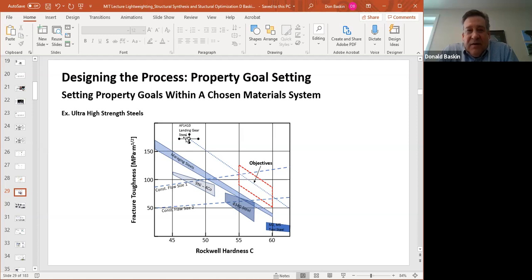Landing gear of airplanes is a big challenge because they take a lot of impact loading. An airplane lands on an aircraft carrier or runway somewhere, and the gear is very small and skinny. You've got this multi-ton aircraft that's landing on those tiny little sticks. They take a lot of stress. And of course, because it's an airplane, it's really critical to make them lightweight. So you do whatever you can to design a material that has the strength to density ratio to handle that type of loading. So AF1410 was developed and is a very strong material. It's also a very tough material. They're able to achieve fracture toughnesses of over 150 megapascal root meters, and at the same time have Rockwell C values between 45 and 50, which translates to, I don't know, a gigapascal in yield strength or so. It's a pretty strong material, but it's not as strong as 4340.